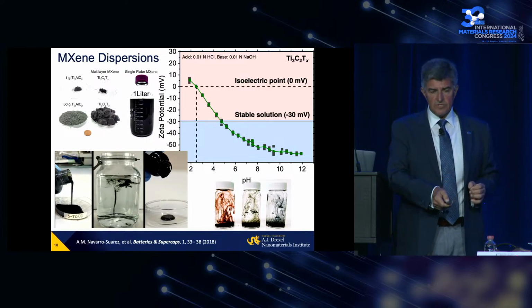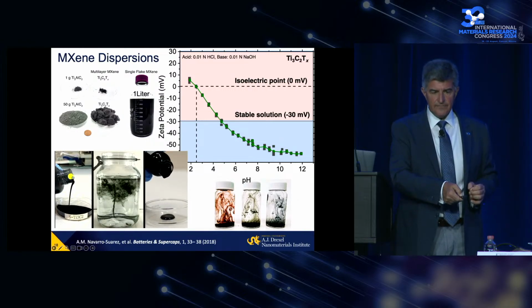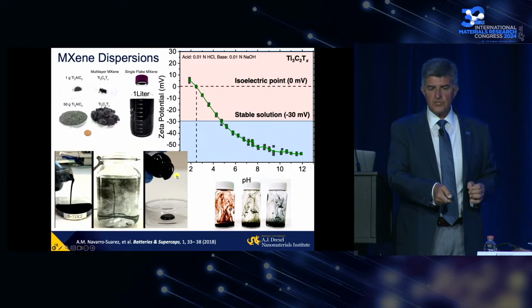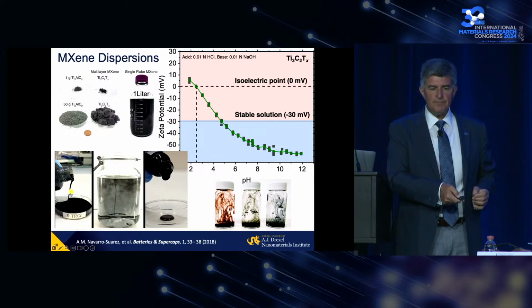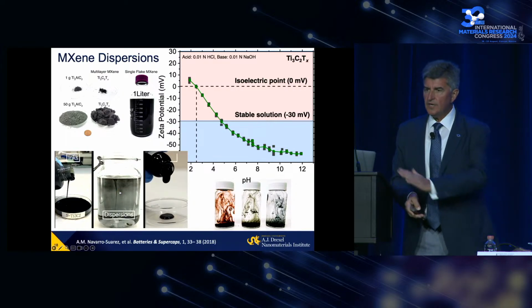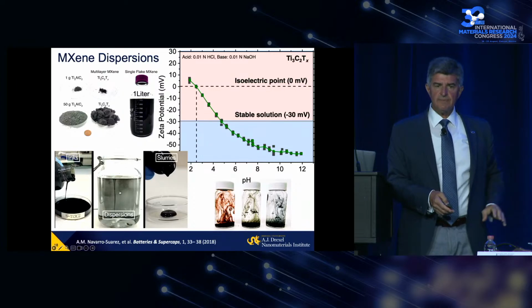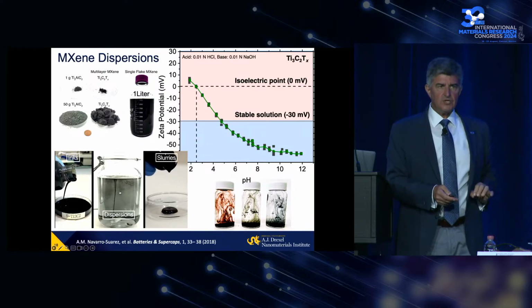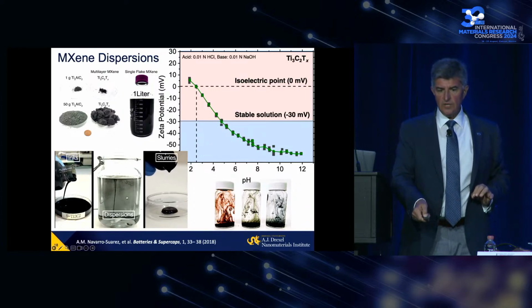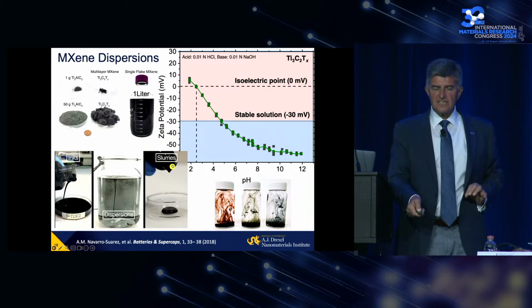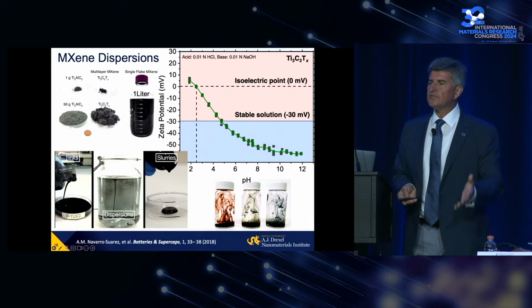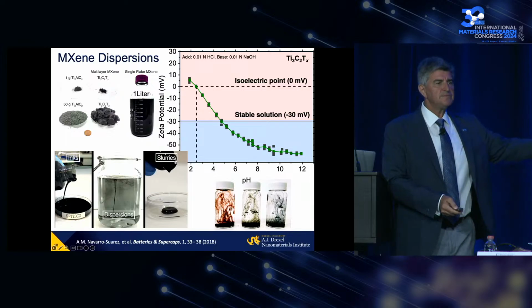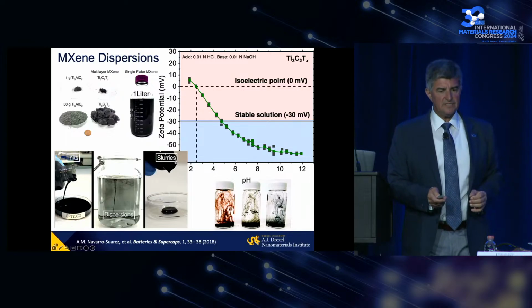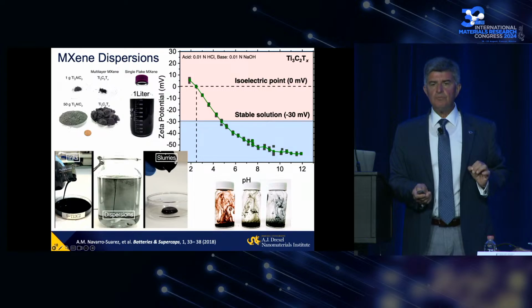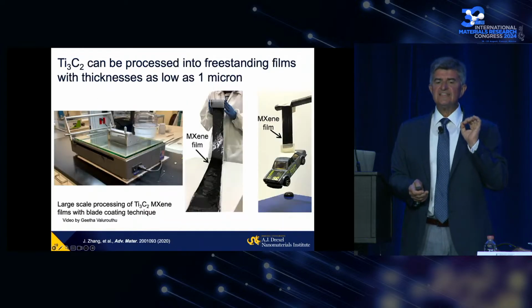When you disperse it, depending on the flake size and concentration, you can make either a very liquid 5 to 10 milligram per milliliter solution for inkjet printing or spraying walls with MXene for shielding or thermal insulation, or you can make a thick slurry which is liquid crystalline. You can draw fibers, make films by doctor blading or screen printing, and you don't need to burn the binder, just dry it.